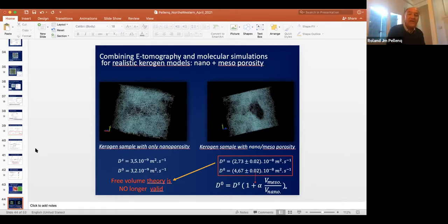Obviously, if we have only nanometer pores, the self-diffusion coefficient will be equal to the actual transport coefficient. This is what we actually calculated. But when we put those big pores in place, this is not the case anymore. But then we found a way to correct that. We relate the self-diffusion coefficient to the transport coefficient through a linear relation with the volume of mesopores, the big pores, divided by the volume of nanopores. So that we can still use the free volume theory; we're just correcting it for the amount of big pores. With that, we are equipped to predict the transport.